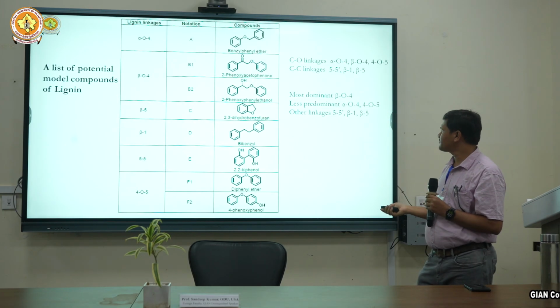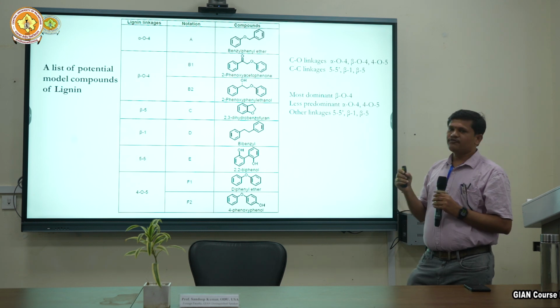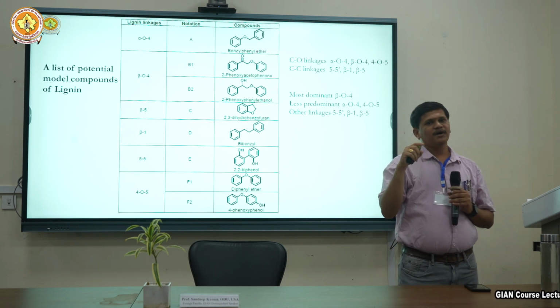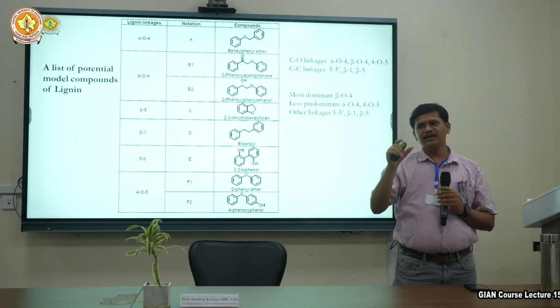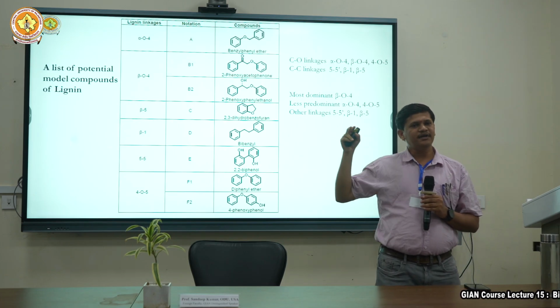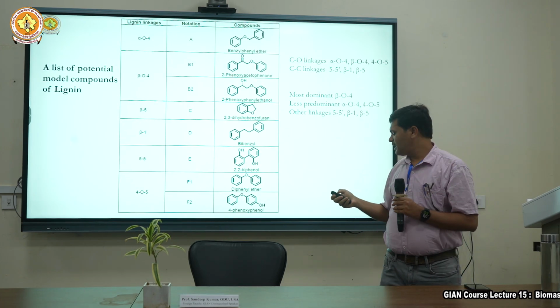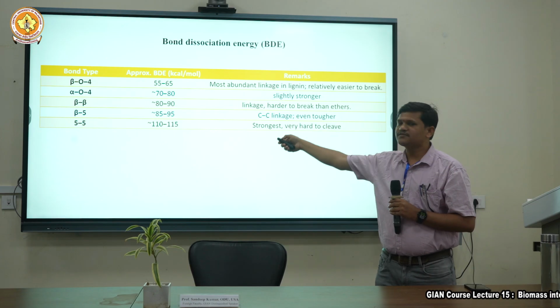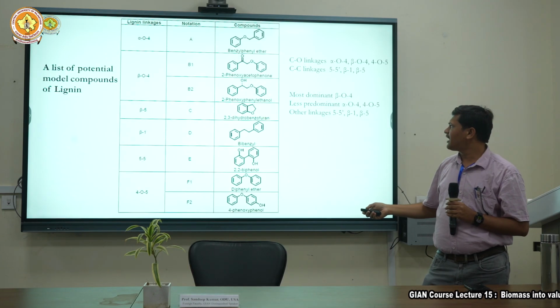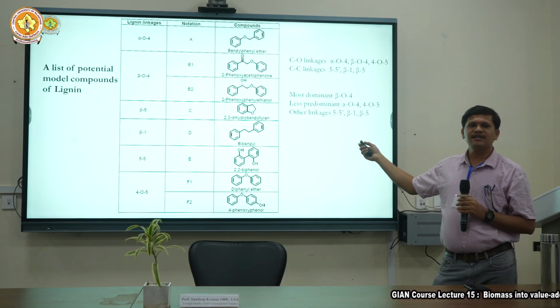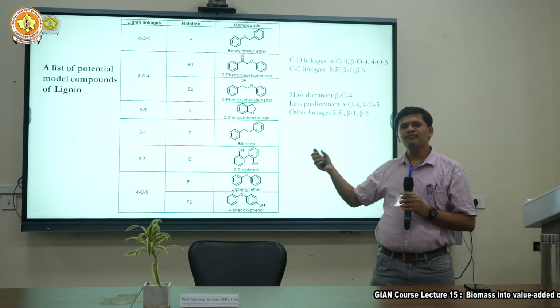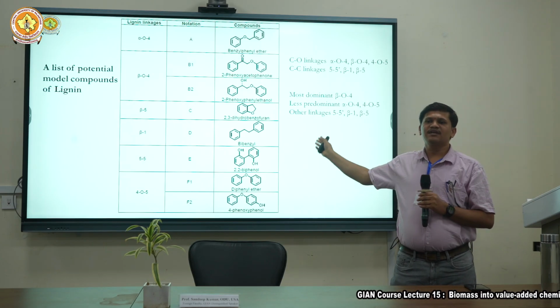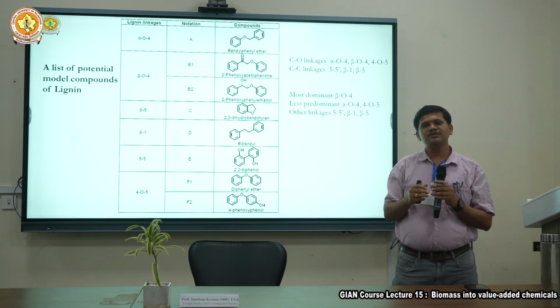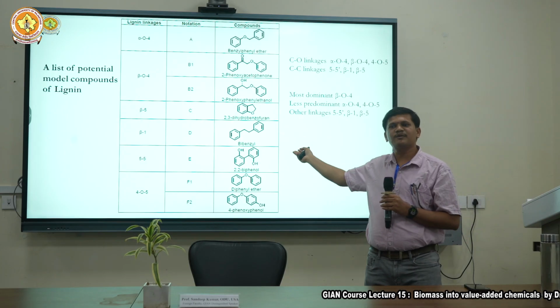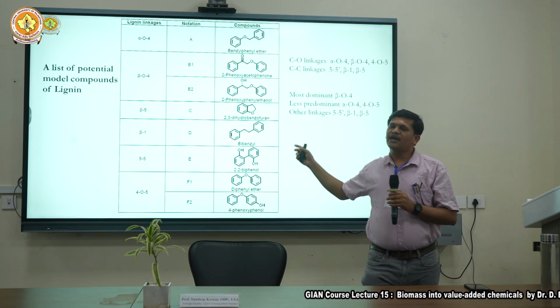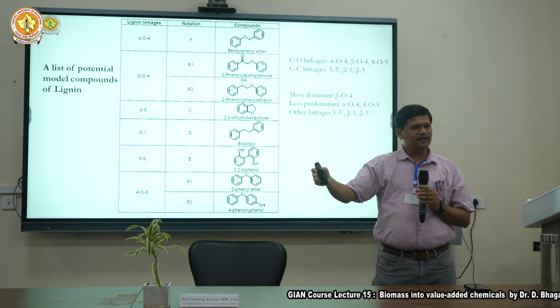And now, if we break down this polymeric lignin compound, and if we break down linkages at all these 5 groups, then we will have these product materials, and this can be considered as a synthetic product of the lignin. So synthetically, whenever we start experiments, first we can do experiments with these chemical components, followed by the real lignin compound.